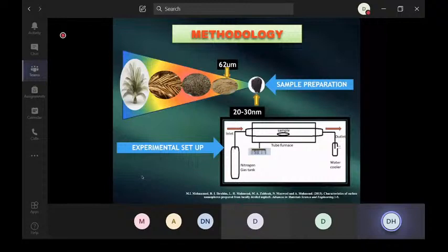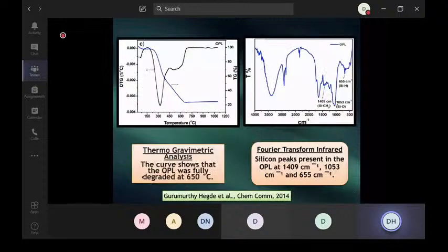But the question is, why did I say we have to use temperatures like 700, 800, 900, 1000? How do we determine the temperature? The first thing is you take a precursor and subject it to thermogravimetric analysis, where you can see the weight reduction taking place. Initially weight loss occurs as the lignocellulosic content reduces its weight. Then as the temperature passes 600 degrees, almost 80 to 85% weight loss has taken place. And above 600 degrees until 1000 degrees, it is a very flat curve. That means all the volatile components are burnt away, and you get only pure carbon. So 600 to 1000 degrees is an ideal temperature range to synthesize the nanoparticle. That's why we synthesized at 700, 800, 900, 1000.